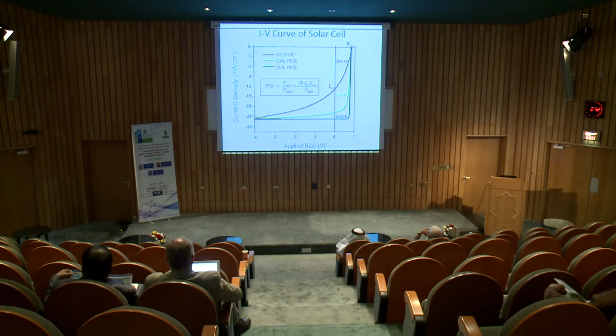Before I go on, I just want to highlight briefly what exactly fill factor is and how it can affect the current-voltage curve in your solar cell. I show here simulated device data showing how fill factor can really affect your device characteristics. The device with low fill factor, the red curve, only 35%, has only 5% power conversion efficiency. If you increase the fill factor by a factor of 2, the green curve, you can easily double the device performance to 10%. If you increase even further to 85% fill factor, you can easily reach a 15% solar cell.